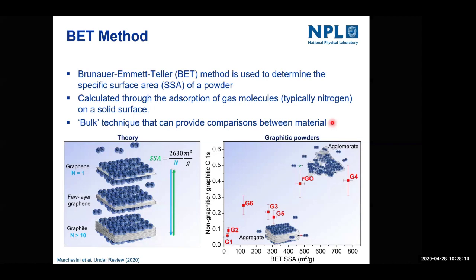So it's a bulk technique. You're essentially putting a lot of powder in a tube, and you're adsorbing gas molecules onto the surface of that powder, and then calculating the surface area from that. Now, again, it's a very powerful technique. I wouldn't call it a fast measurement. It's not Raman spectroscopy, but it's not as slow as doing hundreds of flakes with microscopy methods necessarily. But again, as it's a bulk technique, you have the power of looking at the powder as a whole. And that gives you this specific surface area.